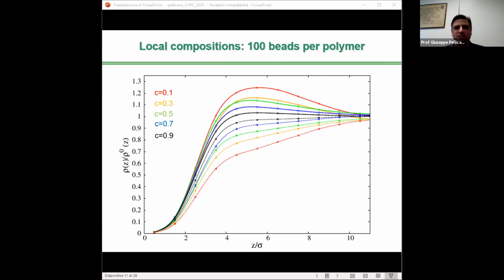So here we look at the reduced density as the ratio between the number density of the two polymer species and their density far away from the interface, which is what we call the bulk density. On the abscissa, as usual, we plotted the distance from the interface. That is the reason the curves reported here all tend towards 1 at long distances, far away from the interface. So in this figure, the reduced density nearby the interface becomes more enhanced, especially at low compositions where the experiments have been performed.